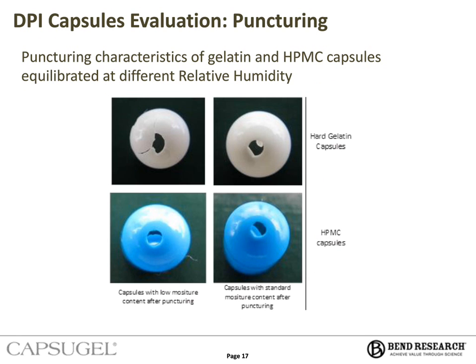If you look at the picture on the left-hand side, these are capsules which have been stored under dry condition on purpose, and you can see that there is no significant change visible on the blue HPMC capsule, the opening is nice and the particle is not detached. The gelatin capsule is cracked and you have high risk to have particle. So this will be one element of choice between the HPMC and the gelatin capsule, depending on the nature and the sensitivity of your formulation to moisture.